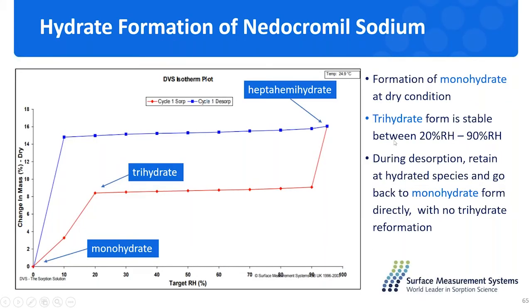So during the desorption, the trihydrate form is not reformed again in the desorption branch. So it's only going back directly to the monohydrate from the heptahemihydrate at desorption steps. So with the DVS technique, it's very clear to study the structure of this hydrate formation, and also we can study the kinetics of this hydration or dehydration.